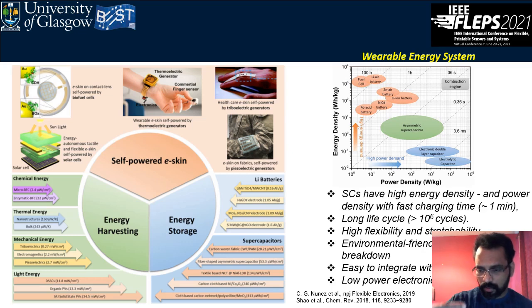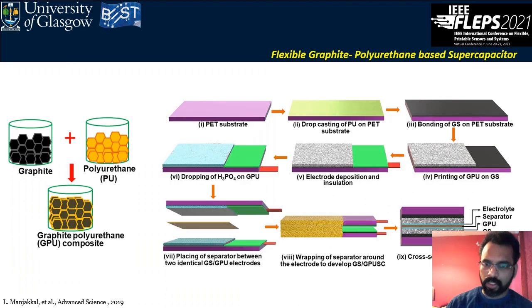that the electrode needs to be flexible. So the material preparation needs to be a low temperature process. In this regard, what we did is synthesize a new material called graphite polyurethane composite. Graphite has very high electrochemical performance for electrochemical double layer supercapacitor fabrication. Here, polyurethane acts as a very good binder in a low temperature process for the graphite composite.